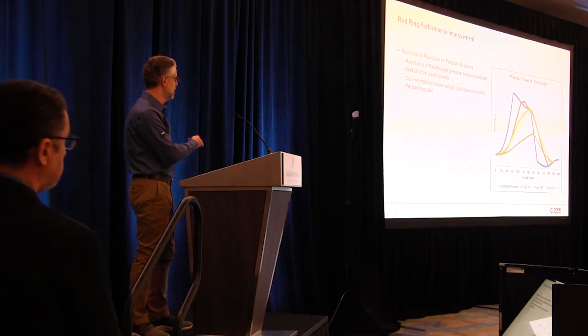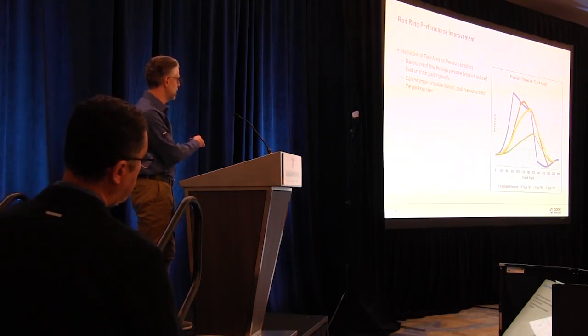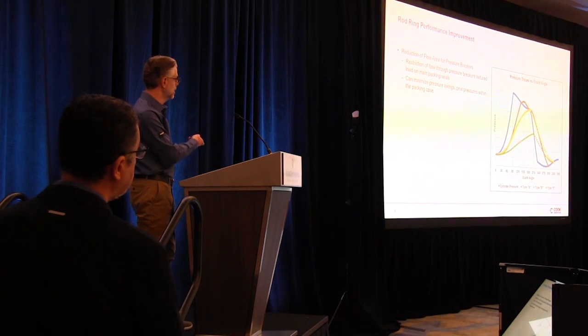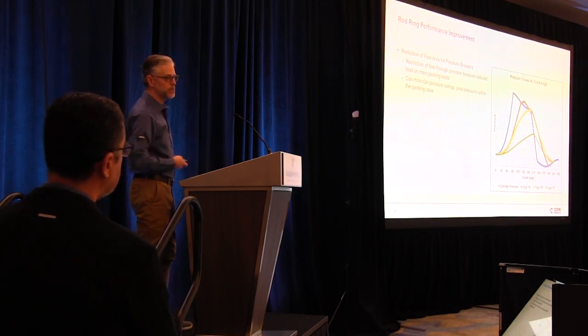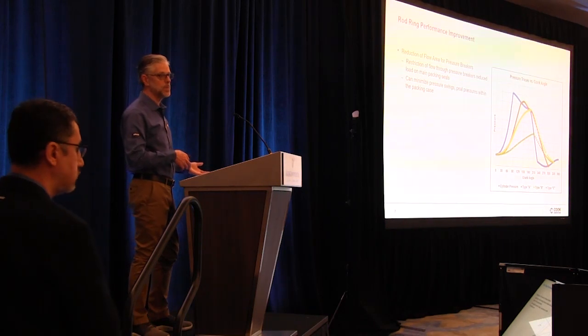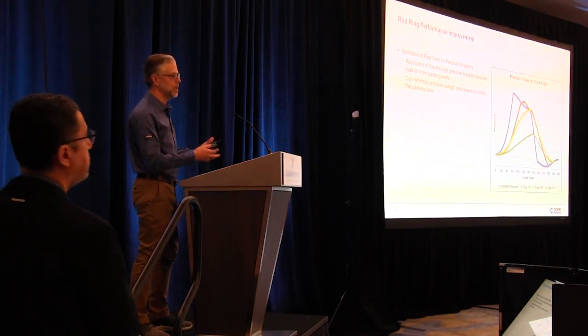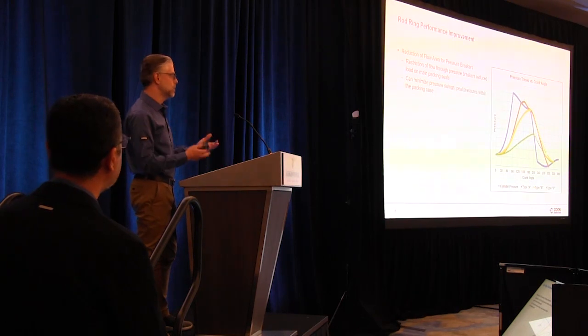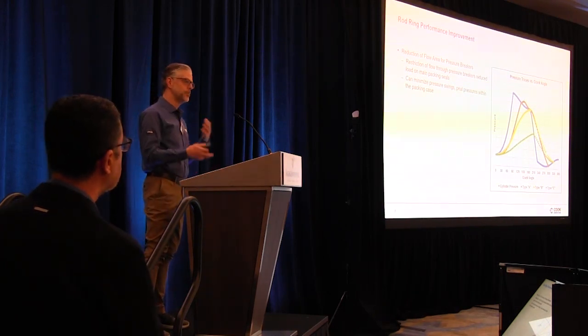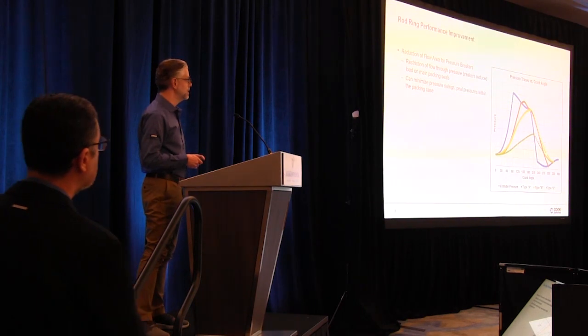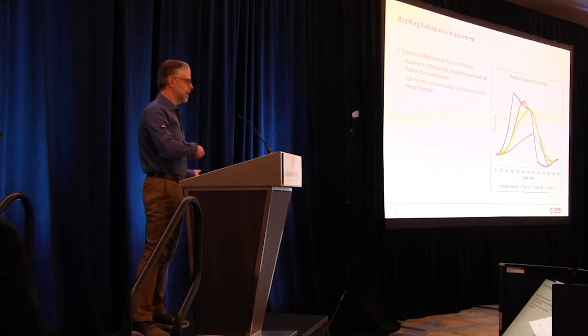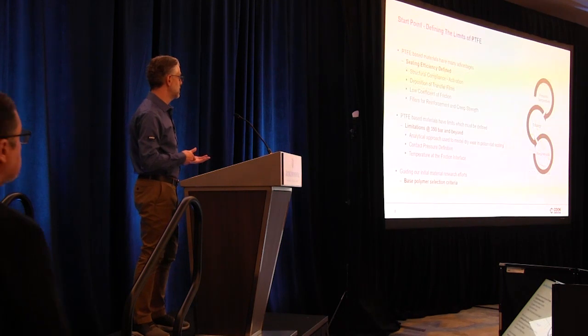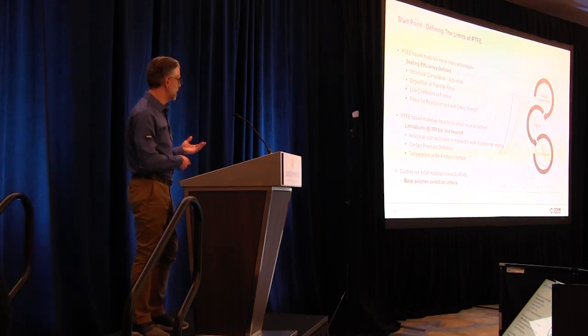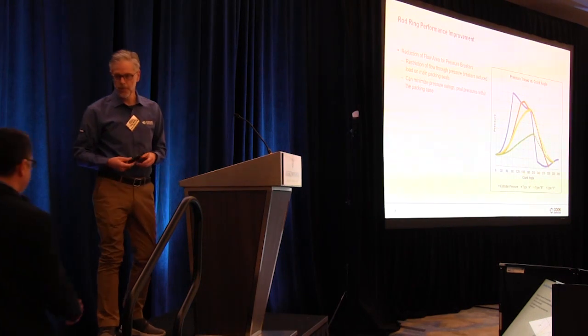out and ultimately get to a position where even with a high pressure swing in the cylinder, the peak pressures and the rate of change of pressure within your packing is minimized, right? So that increases your runtime on your packing, reduces the chance of premature failure, and allows you to run at these difficult conditions. But again, it's always going to come back to the wear materials, and that's really the key to success with these types of applications. So for that, I'm going to turn that over to Burak to talk to us.